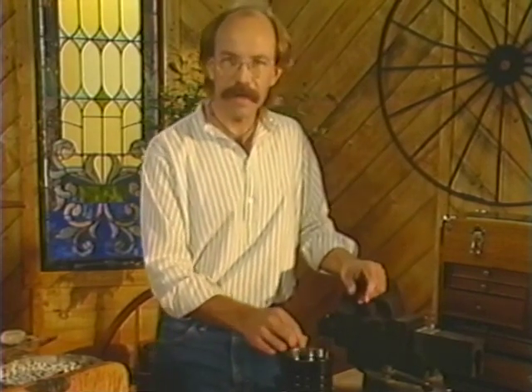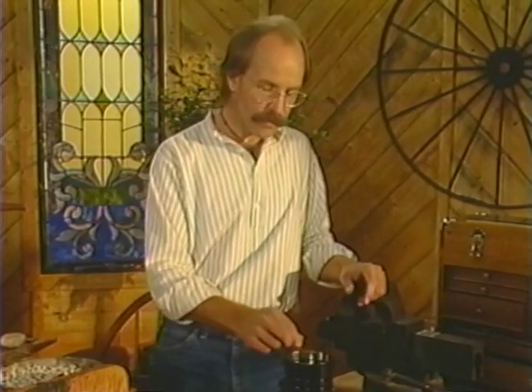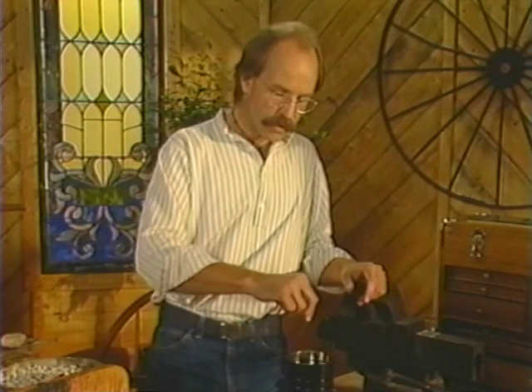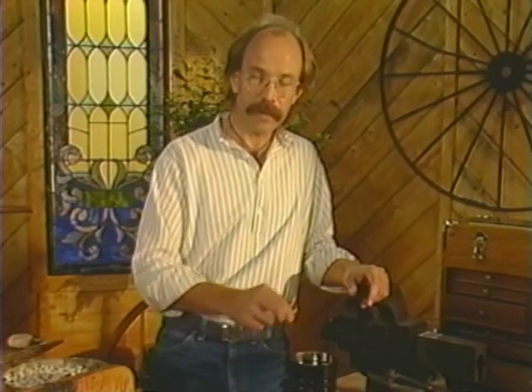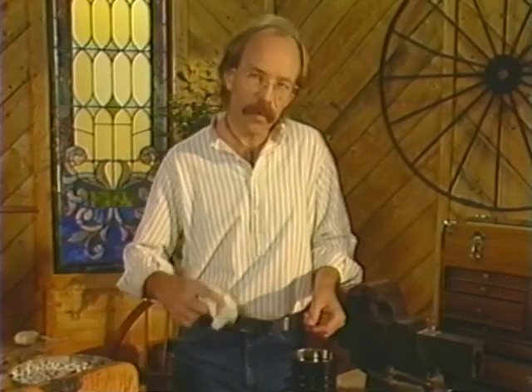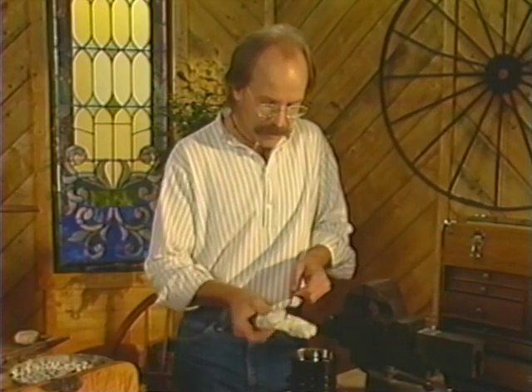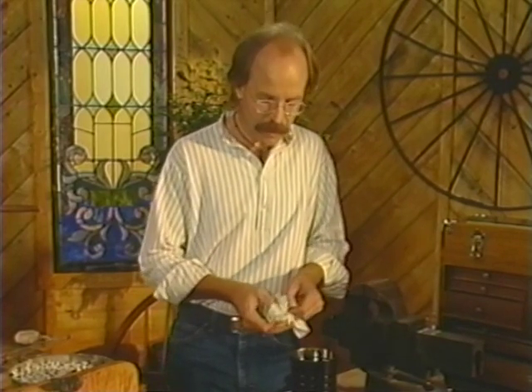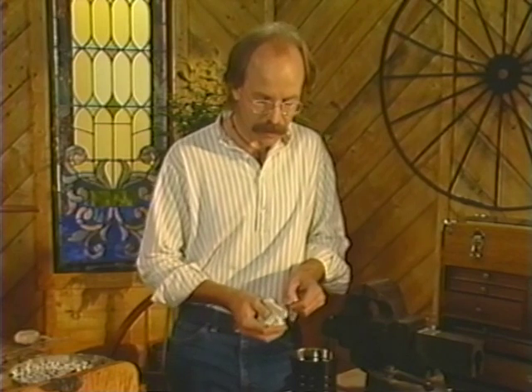Now, the yellow itself doesn't mean anything. It's the fact that it indicates a certain temperature. At that temperature, there are changes going on inside the steel that relieve the brittleness without sacrificing hardness. If I were to wait too long, the longer I wait, the more sacrifice there is. That is, the greater flexibility, but the less hardness.